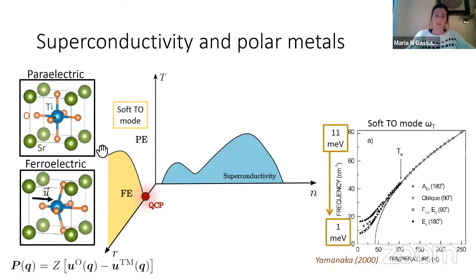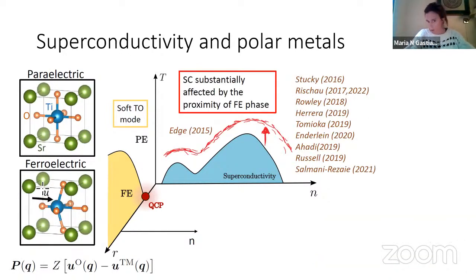Okay, and now if I want to visualize what this mode is, you can think that you have, for example, the titanium and the oxygen cage here moving relative to each other out of phase. This sort of creates an electric dipole, if you want, and then across the transition, this mode would completely freeze out. Okay, so when I discuss today the coupling to the ferroelectric fluctuations, what I'll be doing is coupling the electrons to this kind of polar mode. And why am I